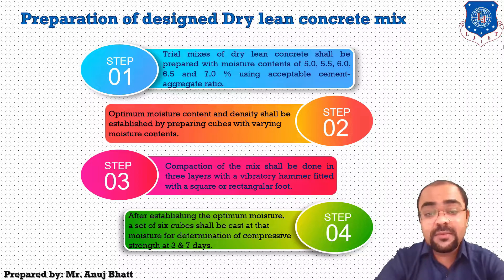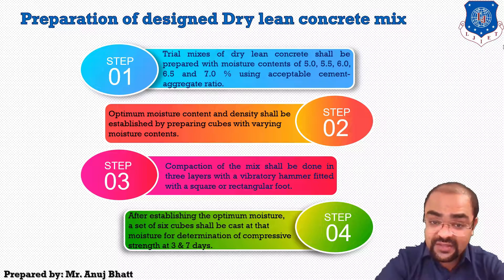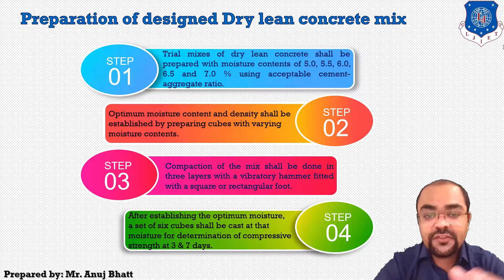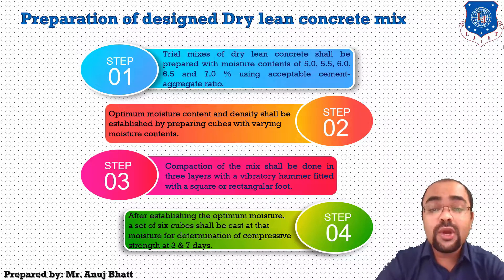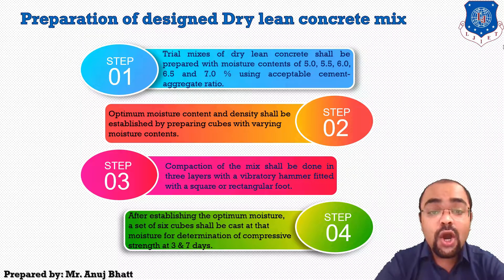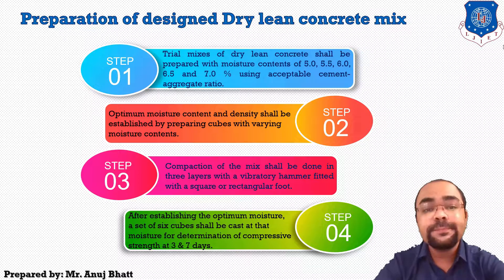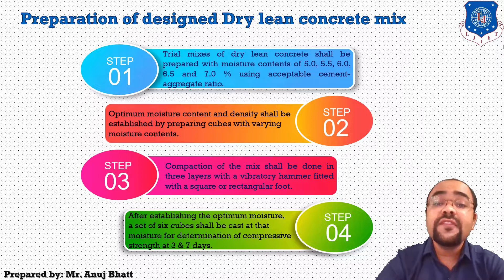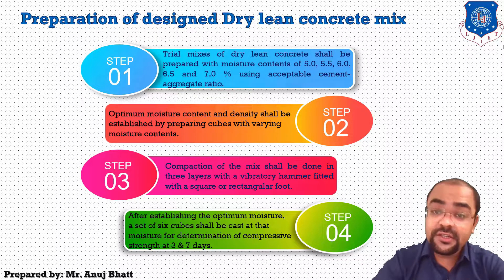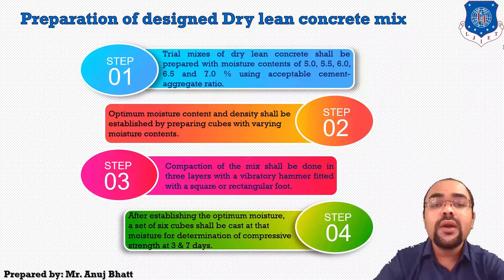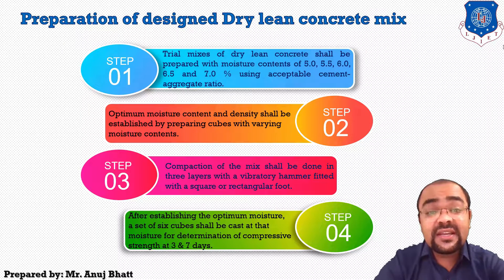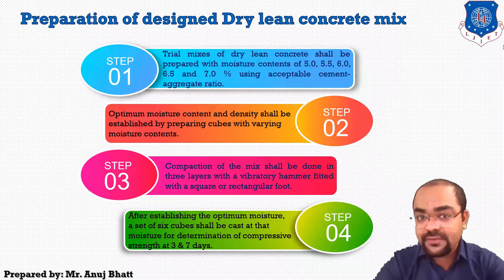The cube specimens prepared with the desirable moisture content should satisfy the strength requirements. Before production of the mix, the natural moisture content of aggregate should be determined on a day-to-day basis so that moisture content can be adjusted. The final design mix should neither stick to the roller nor become too dry — which would result in raveling of the surface or cracking.